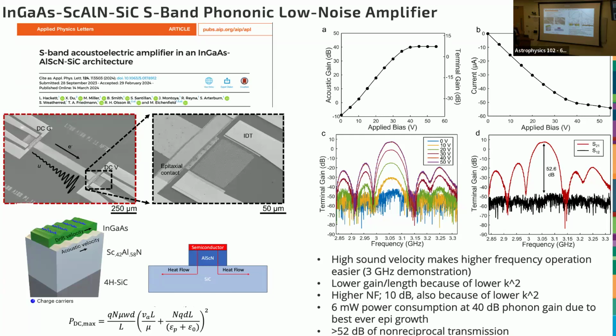So with this one, we're actually able to completely saturate the gain. The physical mechanism for saturating the gain is kind of cool. The electrons are just going as fast as they can go in the semiconductor. This concept of mobility is the linear regime for applying electric fields to carriers. At some point, they essentially reach terminal velocity inside the semiconductor, essentially determined by how often they scatter. That's not even the theoretical maximum of the gain, but it's at least the maximum this device can produce.